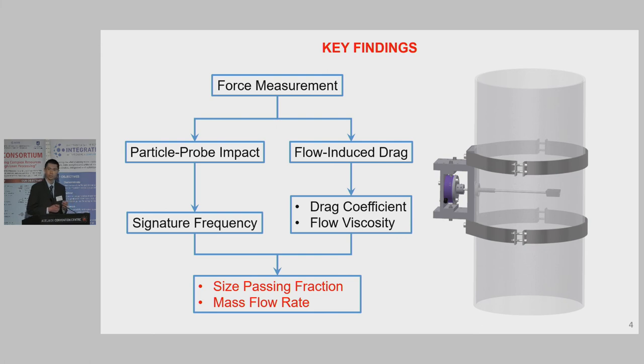For example, if you are interested in P80 of 75 microns, then the sensor will give you a reading in percentage, showing the fraction of particles below 75 microns. In addition to the size passing fraction estimation, the sensor can also tell the mass flow rate using force measurement. So one sensor, two readings. This is a two-in-one sensor.